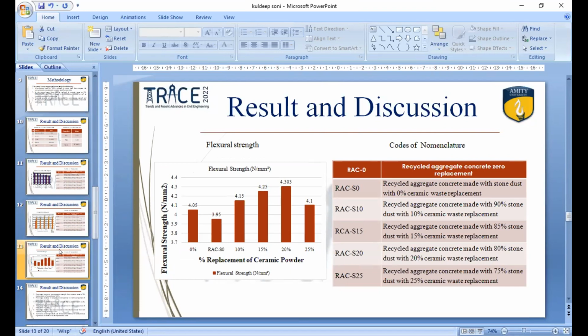Therefore, this concrete is recommended for mass concreting work with vibration. Workability drops in concrete with the increment of ceramic waste. Therefore, this replacement can't be possible in self-compacting concrete. The optimum value of ceramic waste is achieved at 20% with stone dust.